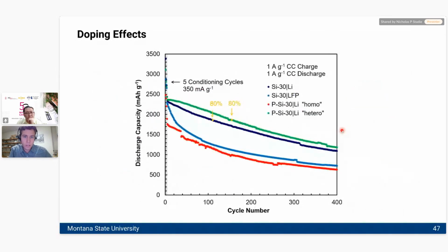Here are some of the best data that we've ever collected. So this is kind of our performance metric today. What we see, the heterogeneous distribution of phosphorus in the lattice, what we call this hetero material right here, in an Si30 format with phosphorus doping, we can achieve values of around 2,000 milliamp hours per gram for around 150 cycles. That represents about 80% of the original capacity after around 150 cycles. So, you know, that is what it is.